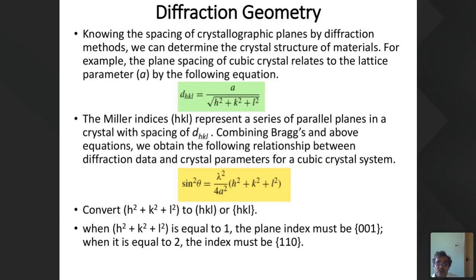Knowing the spacing of the crystallographic planes from diffraction methods, we can determine the crystal structure of materials. For example, for the cubic system the plane spacing is related to the lattice parameter a, so d_hkl equals a divided by the root of h squared plus k squared plus l squared. These are the Miller indices of parallel planes in a crystal lattice. Let us not go deep into this.